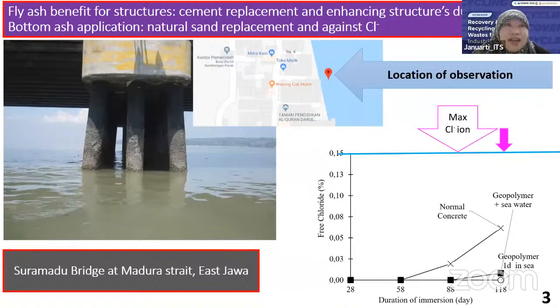We know that fly ash and bottom ash have a lot of benefits for structures, especially to increase durability, especially if we use geopolymer 100% to replace Portland cement with fly ash, it can enhance structure durability. And this picture was taken at one of the locations of piles in Suramadu Bridge at Madura Strait, East Java. You can see also here a lot of barnacles or biofouling attacking the piles.